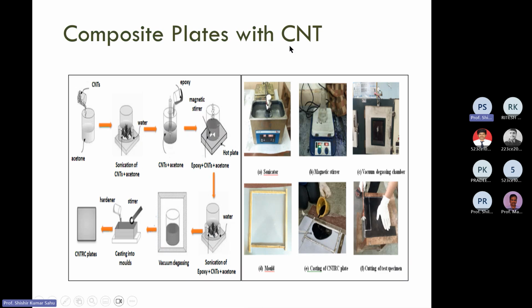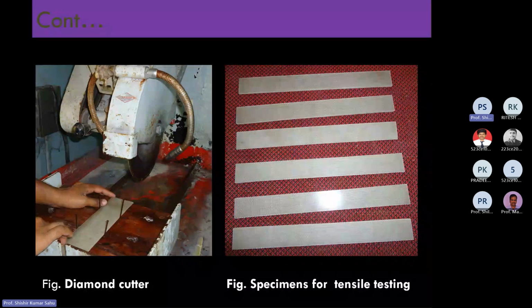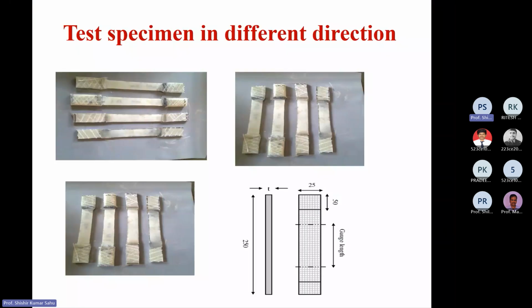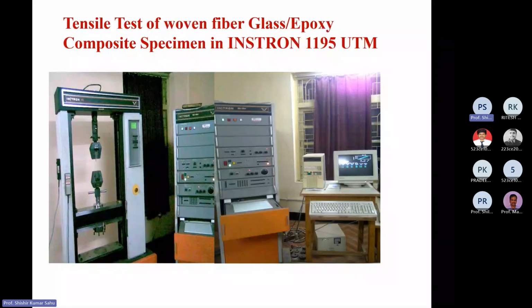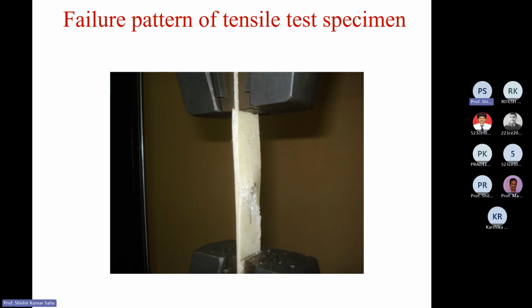So we add carbon nanotube CNT powder in the matrix itself. With some process, these small equipments are being used, not very costly. Using stirring or sonication, all those things have been done, and this is added to the matrix and then with fiber. That way it becomes nanocomposites. So everything we have done in a laboratory. This is the tensile testing. This is the Instron, for tensile test of composite specimens. This is the failure pattern.